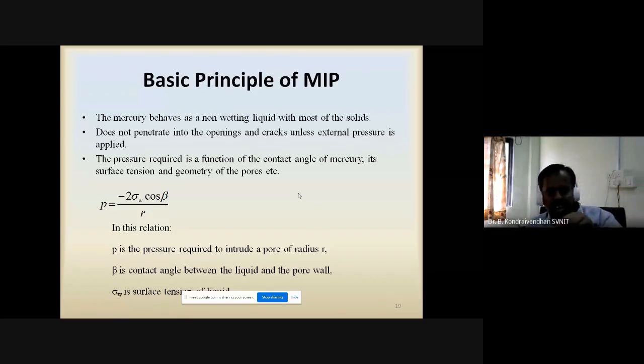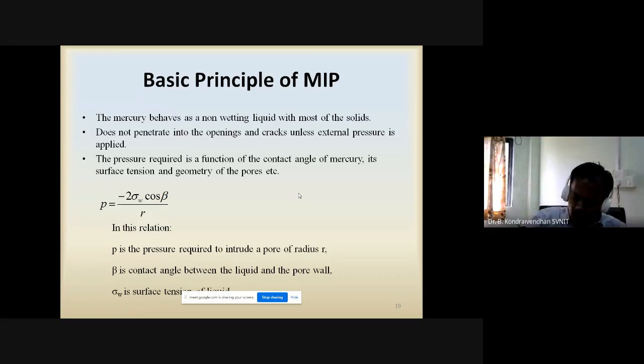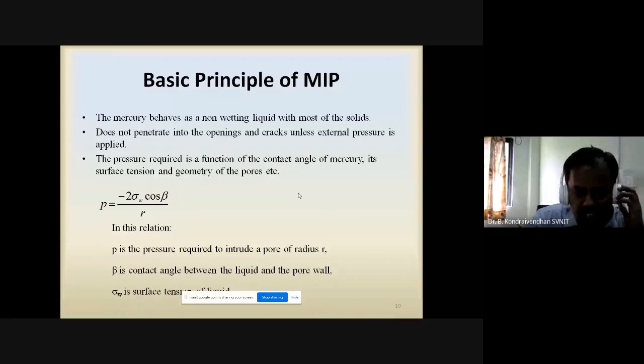So the pressure required is a function of the contact angle of the mercury and also its surface tension. These are the two parameters actually governing. That is the Washburn equation: P equals minus 2 sigma_W cos beta by R. Here sigma_W is the surface tension of the liquid, beta is the contact angle of the liquid, and P is the pressure. That's why MIP follows the Washburn equation, because we are applying pressure to inject the mercury inside the sample.